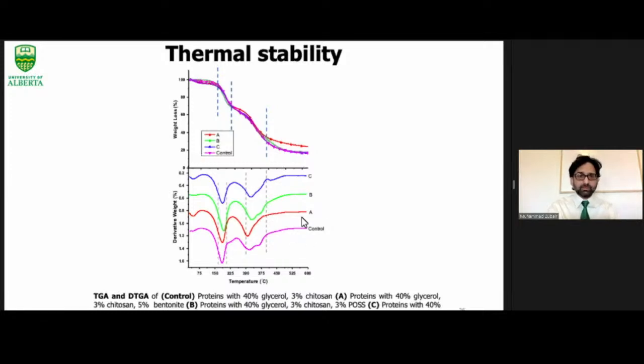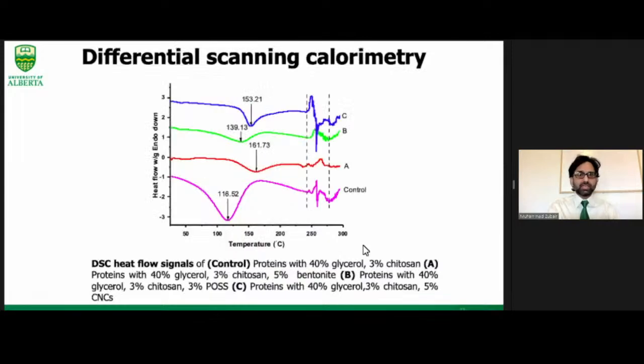However, the protein films containing bentonite have the highest stability among the developed films. The bottom graph shows the derivative weight loss of the films. So we can see that in case of control, the maximum weight loss is around 160. However, in case of C and B, the loss at the end has been decreased as compared to the control film. Furthermore, DSC, differential scanning calorimetry, was performed. The first loss is around 116.52 degrees centigrade in case of control. However, that shifted towards the higher temperature in case of A, B, and C by the addition of the nanoparticles.